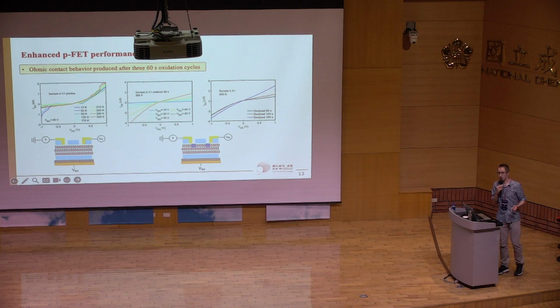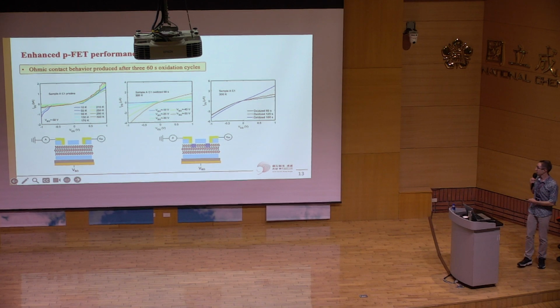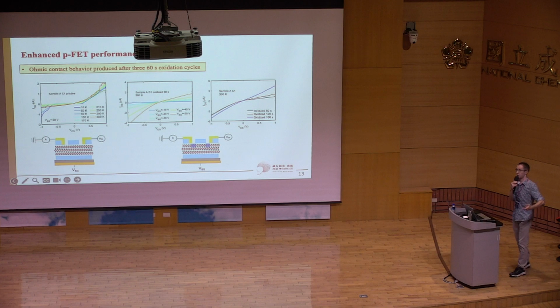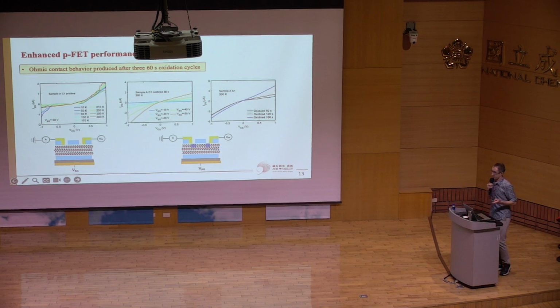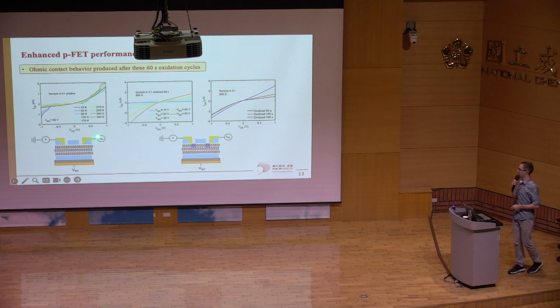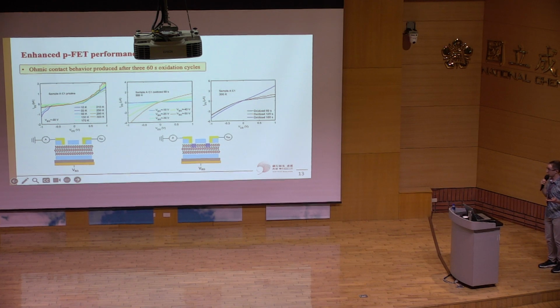So we're at low temperatures, you've removed the thermionic emission part, you've removed the thermal energy from your electrons, so they can't jump over your tunnel barrier. It's only when you go up to higher bias that you start to get a current flow. So that's one key thing to notice from this. The other key thing is that it's asymmetric. So it's telling you that either the contact resistance isn't symmetric, or you've got different levels of doping in your channel area. It's just an asymmetric, non-uniform device.